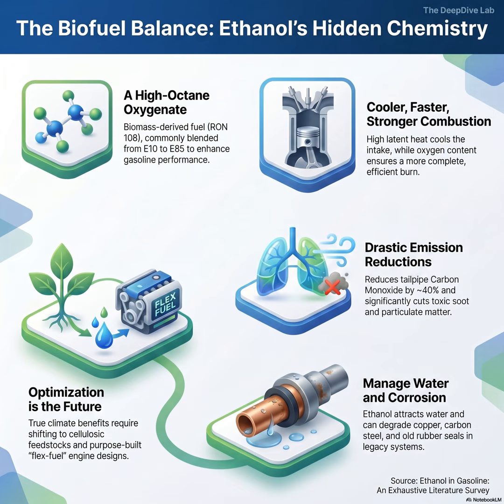If it's acting as an acidic electrolyte dissolving steel, I have to imagine it's an absolute nightmare for the softer materials. You know, the rubber seals, the gaskets, and the plastic fuel lines. The elastomers fare even worse. Fuel system plastics absorb the ethanol molecules, but it's not like a kitchen sponge soaking up water. The ethanol actually penetrates the polymer chains. It sounds more like a dry wooden door swelling up in the frame during a humid summer. The moisture physically alters the structure of the material. That's a highly accurate way to visualize it.